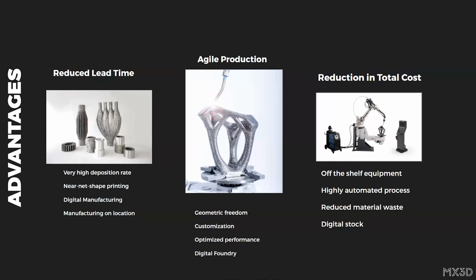Now let's take a look at some of the advantages of wire arc additive manufacturing. The first column is the reduced lead time. Since we're using wire arc, we are having a very high deposition rate. It's one of the fastest metal printing processes. And it, of course, comes, like I said before, with the near net properties. Printing deposition rate varies between 1 to 7 kilograms per hour. And that means that